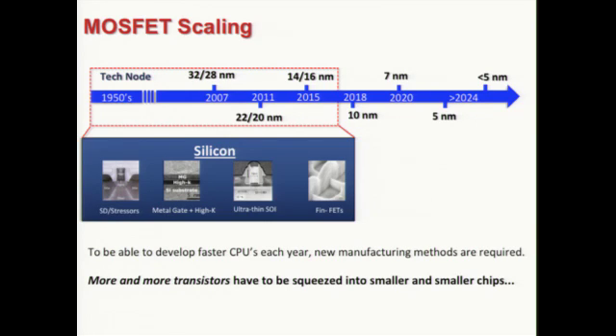But as I said, silicon has reached its physical limit, because right now, for a channel length of 15 nanometer, the silicon thickness is about 5 nanometer. The rule of thumb is that the channel thickness has to be about 1/3 of the channel length. And this 5 nanometer down to 4 nanometer, I would say, is really the physical limit of silicon. Going further down and making it thinner, silicon would not behave as a good semiconductor anymore, because the surface states would dominate the performance of the channel, so the mobility would degrade, and both on current and off current would change, so the device performance would be very bad.